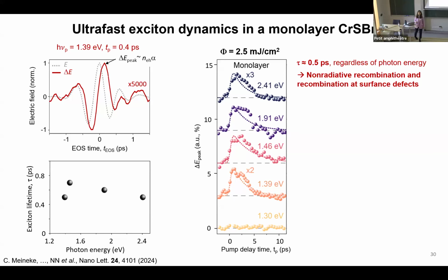So it means there are some non-radiative recombinations at play. Also, when we calculated what should be the recombination time for a radiative channel in our monolayer, we found around 1 picosecond. Our recombination is still faster than even the radiative recombination. So we understand that we must have a high contribution of non-radiative channels together with the scattering with defects or impurities that are potentially present in the monolayer of chromium sulfide bromide. This explains this ultra-fast relaxation and recombination dynamics of the exciton to the ground state.